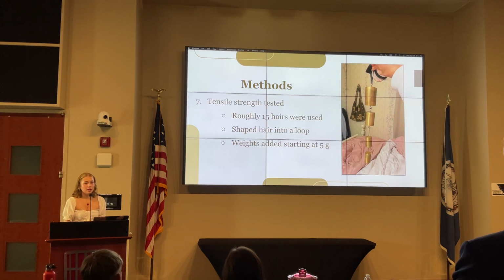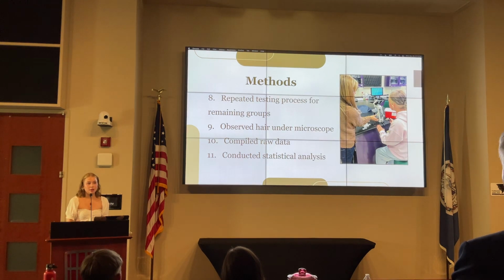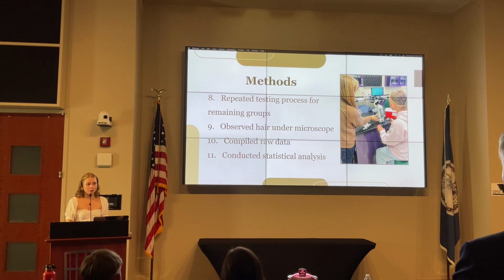The tensile strength of the hair was used as the basis for damage comparison. Roughly 15 hairs were cut loose from the fabric binder and formed into a loop shape that the hook weights could attach to. I added weights starting from 5 grams until the hair broke. Tensile strength by definition is the maximum load a material can withstand before breaking. Therefore, the last supported weight was determined to be the tensile strength. The same tensile testing process was repeated for the remaining color groups.